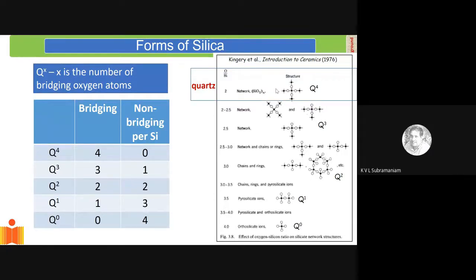So that's the reason why we don't use sand typically as a replacement of cement, because while sand is rich in silica, or sand is rich in silicon, the silicon exists in an oxide form, where basically it is coordinated, or combined with 4 oxygen atoms, in a very stable crystalline form. Whereas when the silicon is combined with 3 or a lesser number of oxygens, it exists in an amorphous form. It forms a network, which is shown here. And that form of silicon is in a reactive form. That means it can actually enter into a chemical reaction.